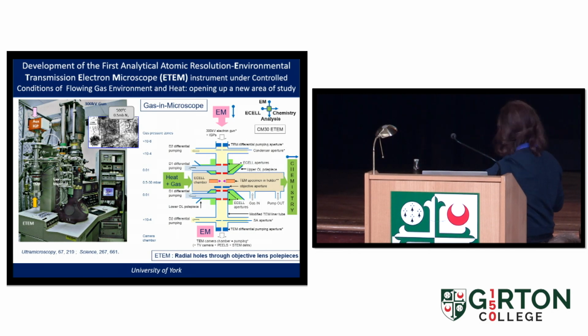So what we did was use the sample chamber itself as a chemical reactor. So that basically saved us using an ex situ cell, because if you put an ex situ thing, unless it fits extremely well, you will have some slack and some blurring of the image. But here, by using the sample chamber itself as a chemical reactor, we could make everything very stable.